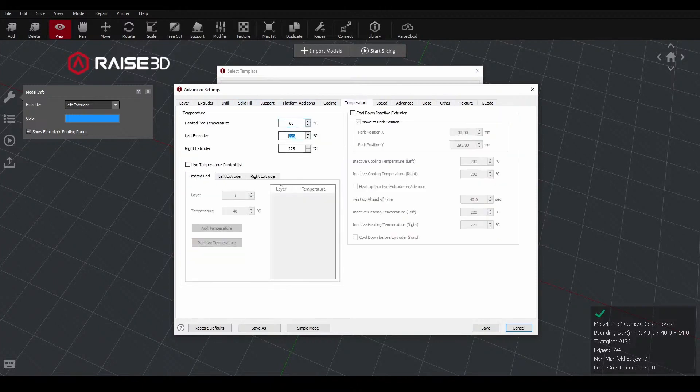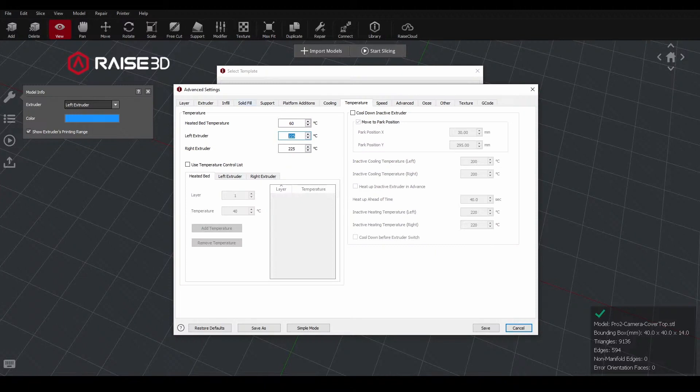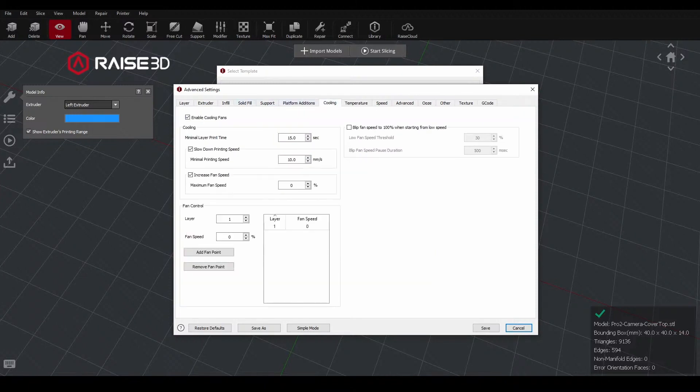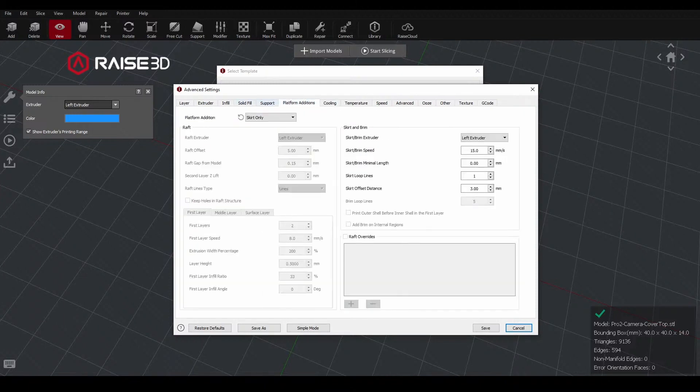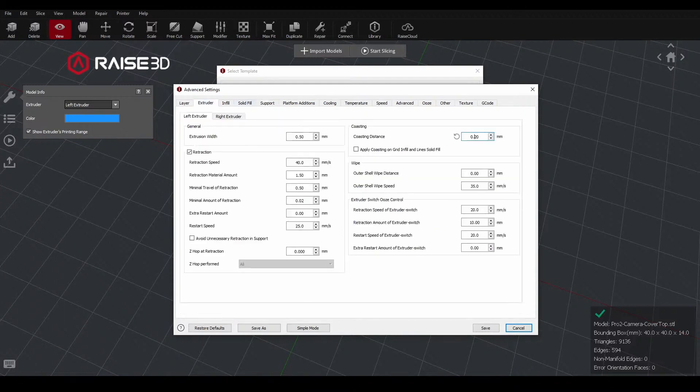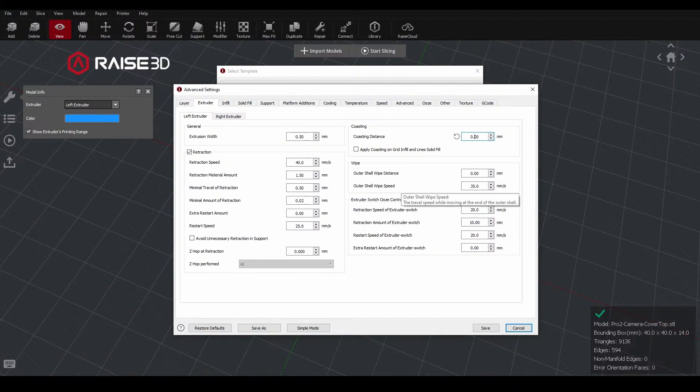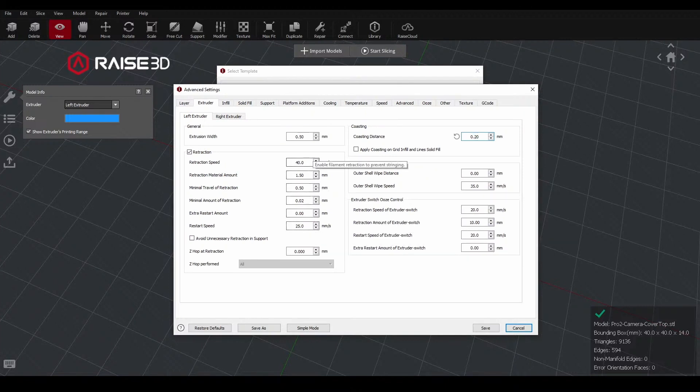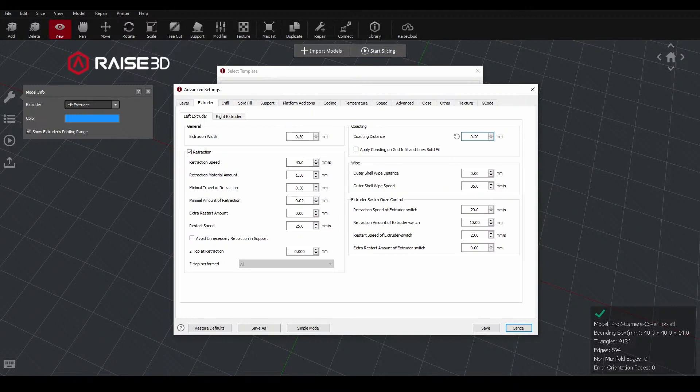Other things in here is adjusting the temperature can help. Typically I'll run our TPU now at 230. The Polyflex template runs at 225, so it's a slight temperature difference there. But I've had the best results running it at 230 on my own. It should work with the same cooling, support structures, and the other things that I had changed for these portions. If you're working with the outer shell wipe distance, wipe speed, or if you're trying to dual print, pretty much the main things you'll be changing for reducing the oozing is messing with the temperature a little bit. And then the retractions and the coasting distance will cut down on the stringing as well.